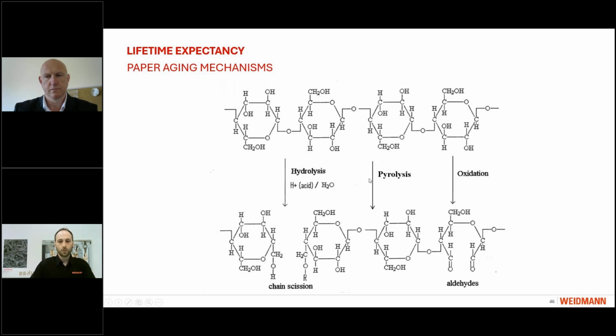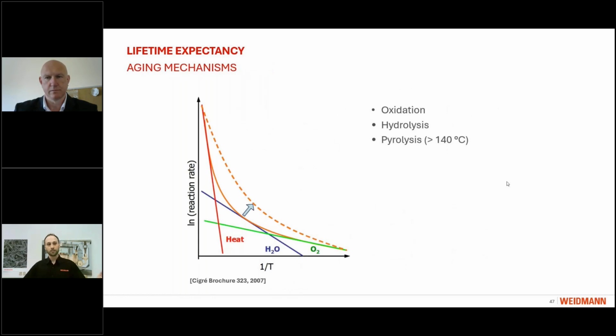Then we have the pyrolysis, which is also a chain rupture that is governed by high temperatures, and oxidation. Here, I think you all know this image very well. When you cut an apple, you have two nice and white sides. You let it lie on the table and they get brown. So this oxidation, of course, needs oxygen. Now, when we look at the overall rate constant, we can divide this into these three processes, where we see that oxidation is actually the lowest temperature rate, then the hydrolysis is somewhere in the middle, and pyrolysis really takes place at elevated temperatures, starting from 140 degrees Celsius. Now, with that in mind, we can ask ourselves the question, how do I need to dry my material to have the least amount of degradation? And this we can see in the next slide.